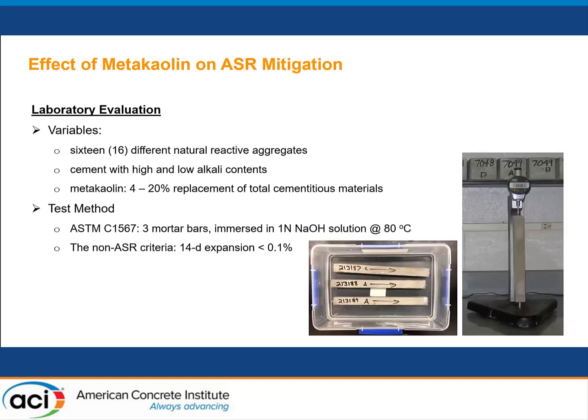For the ASR mitigation study, we're using the ASTM C1567 test method, which is a rapid test method. Basically, you immerse a mortar bar in a 1 normality sodium hydroxide solution and store the specimen at 80 degrees Celsius. According to the standard, you want to achieve expansion less than 0.1% at 14 days.